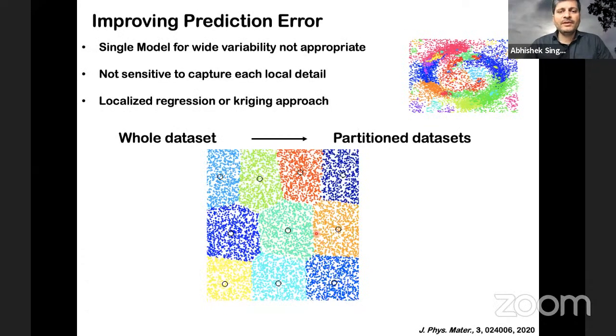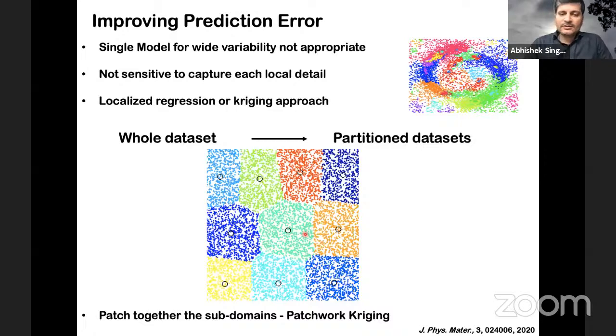So we created what we call a Kriging approach, wherein we develop local models for different classes of material, with a condition that the models are continuous at these boundaries, right? So if a model I created for the blue part and the green part, they both should give me almost similar answers for the data points which lie in this boundary region. That is the condition which you apply and then develop a model. So these individual models are going to be very, very accurate and highly powerful, much more than the global model. However, now we have a set of models which does the job rather than one single model. And this is also known as patchwork kriging.